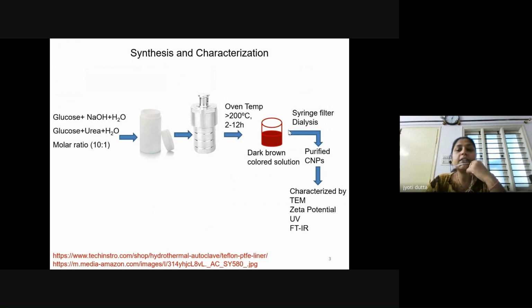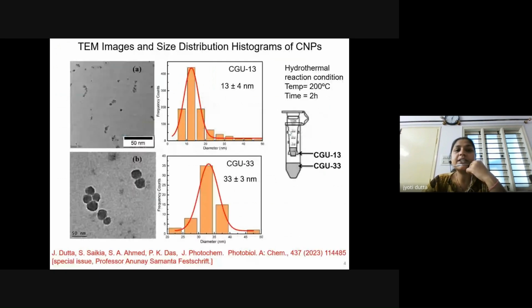And these purified carbonaceous nanoparticles, which we have abbreviated as CNPs, are characterized by TEM, zeta potential, UV and FTIR. So these are some TEM images and size distribution histograms for the CNPs. On the side, what you can see is the filtration method. For this particular set of CNPs, we observed that from the same reaction mixture, we can isolate two different sizes using centrifugal filters, which you are seeing on the side. The temperature for this particular carbonaceous nanoparticle synthesis was 200 degrees centigrade, and the reaction time was 2 hours. We observed that there are two sizes which we can isolate from this set of nanoparticles: one is 13 nanometer and another is 33 nanometer. These two sizes were isolated in two different filter regions of the centrifugal filters.